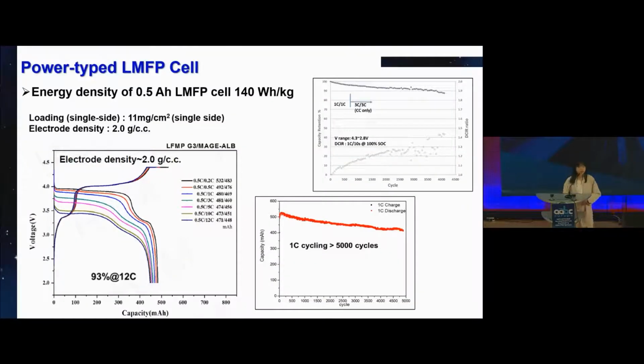So we have successfully developed the power type LMFP cell. It shows the high rate discharge capability at 12C and exceptional cycle life over 5,000 cycles. Besides that, by blending soft carbon and graphite, you can see that the cell can be charged at high rate, at 3C charge and discharge, and retained about 85% of the capacity after 4,000 cycles.